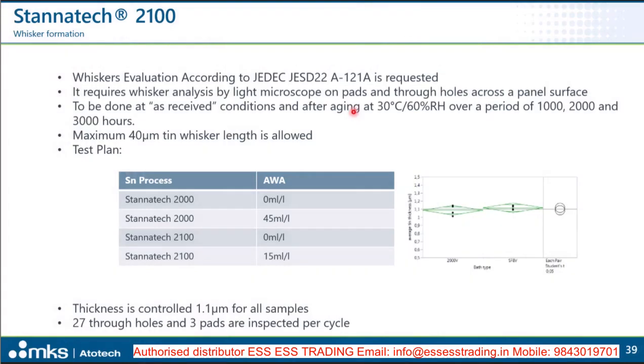Finally, a few words about whiskers. There are certain standards which need to be fulfilled. So for the Stannatech 2000, we have already implemented the so-called anti-whisker additive, which is added to the plating solution to prevent whisker formation in the plated immersion tin area. What was done here was to check different concentrations of the anti-whisker additive, which is also applied in the Stannatech 2100, so it's the same approach, and then to check the whisker formation after aging of 1000, 2000 and 3000 hours in higher humidity.